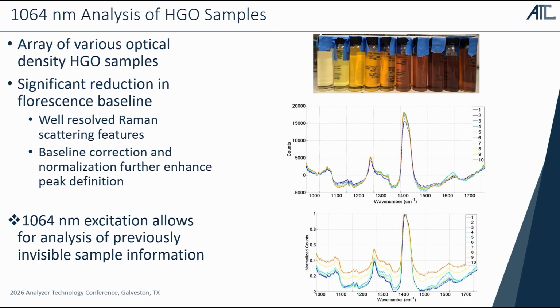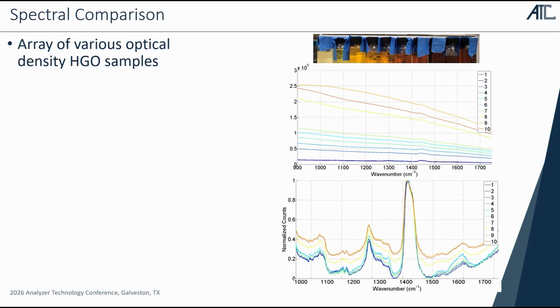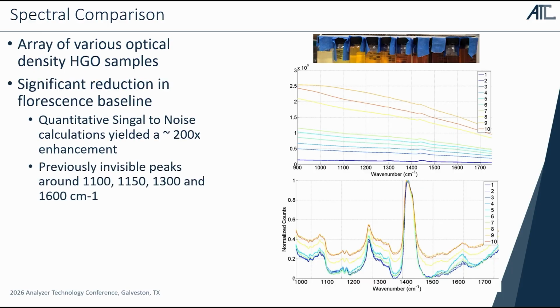And so this is important because it allows us to take some of these peak intensities and integrals and peak positions, and it allows us to go back and do some chemometric modeling so that we can actually use it to quantify properties such as pour point and viscosity, and I'll show some of the modeling data that we've gotten with this as well. And so when you do a side-by-side comparison of the two, you can see that obviously there's a significant enhancement in your signal-to-noise ratio when you quantify it. It's kind of maybe not the most sensible thing to even try to quantify signal-to-noise on the 785 samples, because essentially that background is essentially all noise, and so you get a significant enhancement in the signal-to-noise ratio comparison, and that's important again for identifying peaks for when you're doing modeling as well.